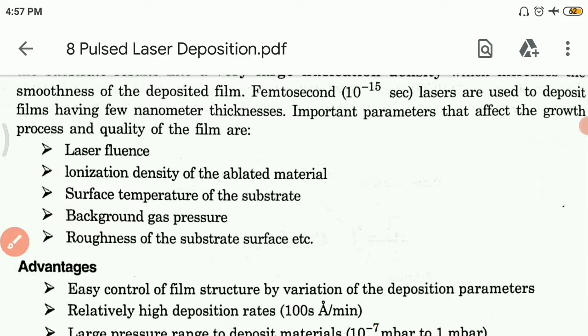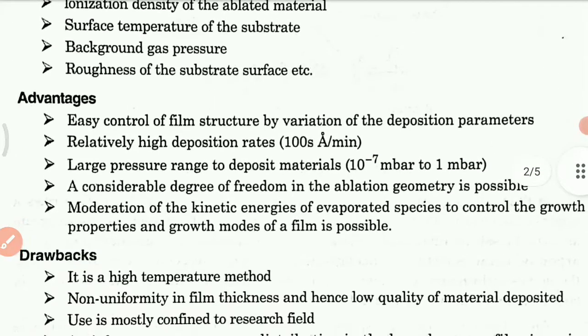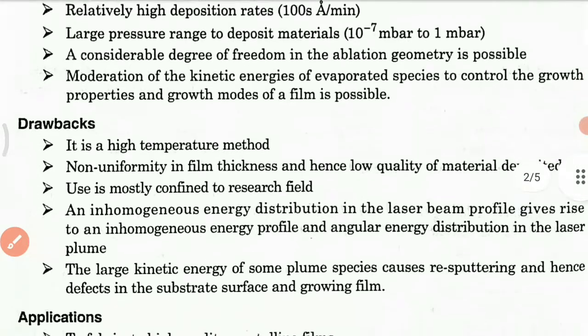Now let us see some of the advantages of this PLD technique. First, we can easily control the film structure by variation of the deposition parameters. Then it has relatively high deposition rates, around 100 angstrom per minute. Then it has a large pressure range for depositing materials, ranging from 10 to the power minus 7 to 1 millibar. A considerable degree of freedom in the ablation geometry is possible in the PLD process. And finally, moderation of the kinetic energy of evaporated species in order to control the growth properties and growth modes of the film is possible.